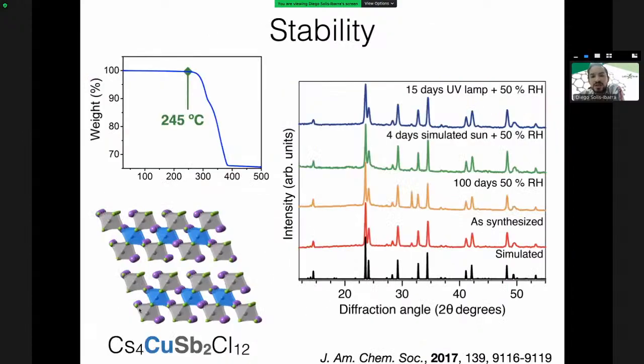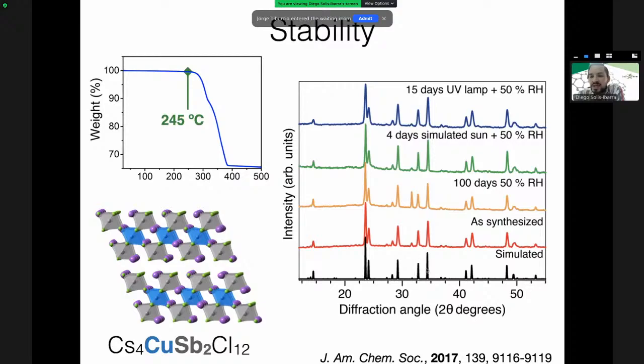We also show that the stability of this material was really great. It has a great thermal stability. If you want a material for solar cells, you want it to be stable to high temperatures because it's going to be heating while exposed to sun. And as compared to other perovskites, as I mentioned, we exposed our material to relatively high humidities, and we also combined humidity plus illumination, like 4 days of simulated sun or UV and humidity, and the material stayed put in all of these conditions. We see no sign of degradation, which we think is a really great sign of stability, and a really great step towards the stability that we're looking for in these materials.